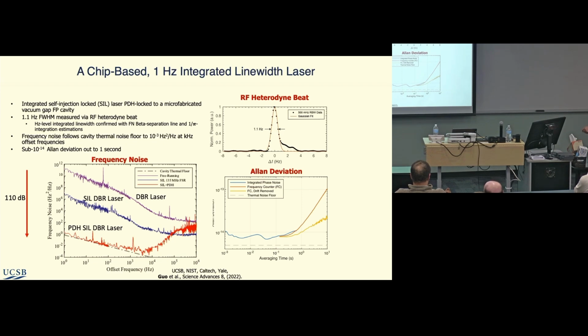So here's the Allan deviation plotted. This is 1 second here. And this orange curve is the drift of that cavity due to temperature fluctuations over time. And if we remove that drift, then you get good Allan deviation out to, say, 10 seconds or minutes.